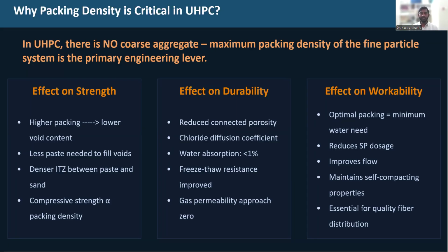But again, durability can also be considered a key role in the design of UHPC, because just because we are getting higher strength in the concrete, let's say 150, 200 megapascals, we cannot exactly say that it might yield better durability conditions. Let's say the permeability or the porosity or the sorptivity conditions or the chloride permeability or acid resistance, any of these, carbonation tests, any of these things also have to be tested, because when we construct structures with UHPC materials, we expect the structure to be there for at least 150 plus years of age. So when we are constructing a structure which will stand for 150 plus years, utmost preference has to be given to durability as well, alongside the strength.